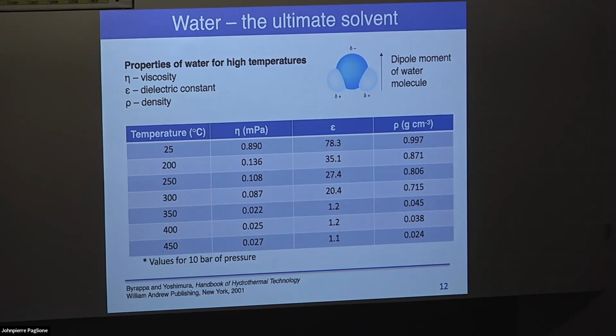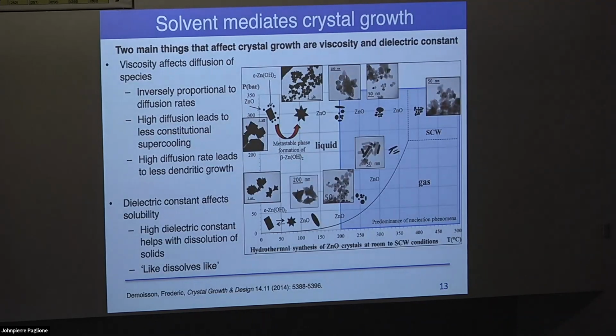So depending on what you are worried about dissolving, water can help at different temperatures, and you can span that whole region. The important thing is that the solvent you use is what helps mediate the crystal growth. There are two main things that mediate your crystal growth: the viscosity, which I showed you how water changes with respect to temperature, and the dielectric constant, because the dielectric constant determines what's going to be actually soluble in your system.